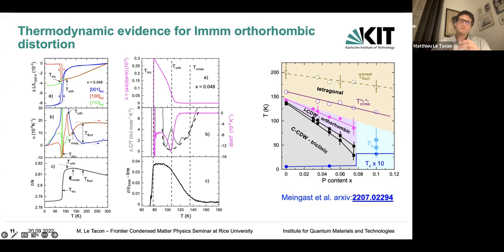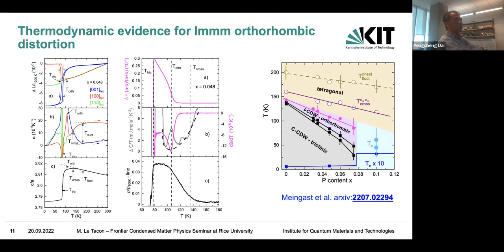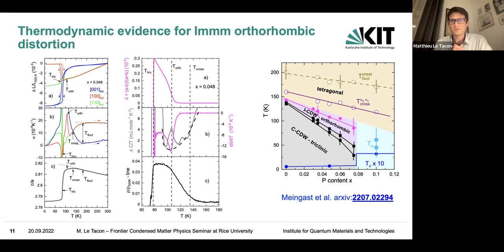And then at some point this turns down. So at some point you either slow down the compression of A or accelerate the compression of C. Christophe could comment better on that. But this takes place at a temperature very close to the temperature at which we start seeing the broadening of the Raman phonon. I think all those things are coupled. From the thermodynamic point of view, this is why Christophe called this the fluctuation temperature. There's an onset of fluctuations here,